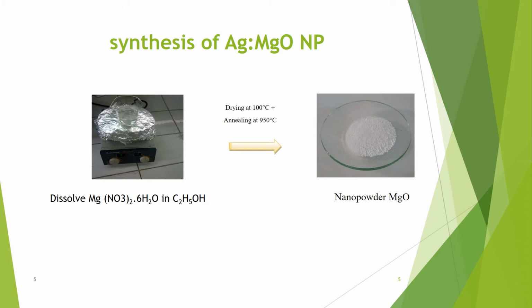Magnesium oxide nanoparticles were prepared by the sol-gel method by dissolving magnesium nitrate hexahydrate in absolute ethanol under magnetic stirring for 24 hours to obtain a white gel. After that, the mixture was dried at 100 degrees Celsius for 24 hours and annealed at 950 degrees Celsius for 36 hours to obtain magnesium oxide nanopowder.